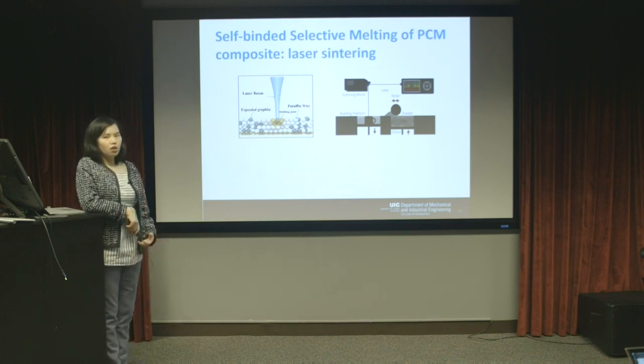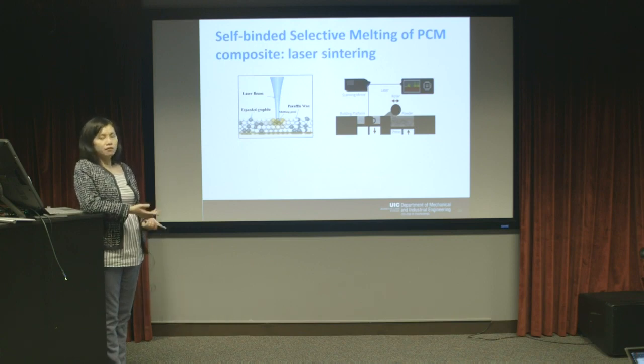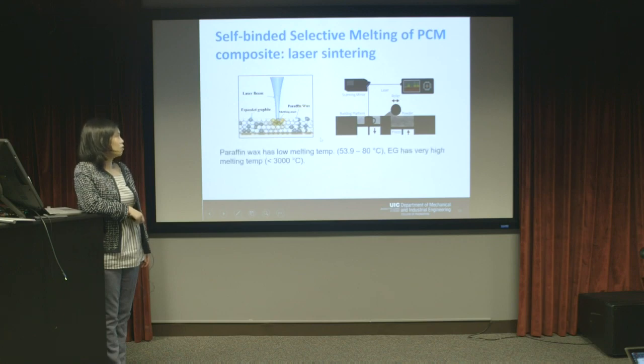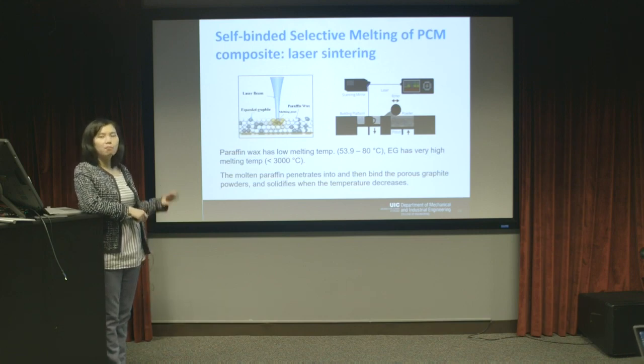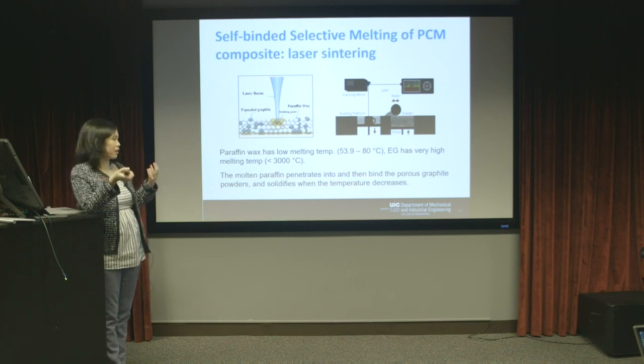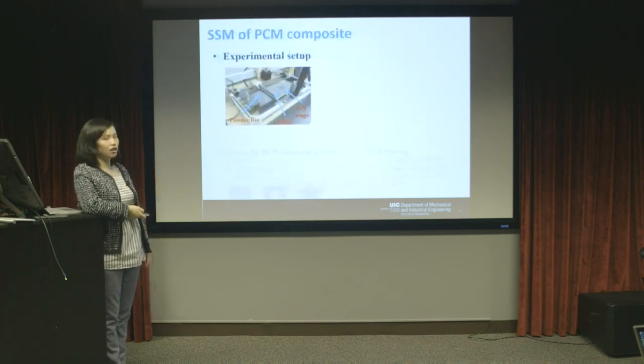So then we thought we could investigate the selective melting or selective sintering process to process a mixture of expanded graphite powder and paraffin wax powder. Because the paraffin wax has a low melting temperature, and the expanded graphite has a very high melting temperature, we can use a very low power laser to melt the paraffin wax. And the molten paraffin wax works as a binder to bind the expanded graphite powders together. Then we can make the composite.